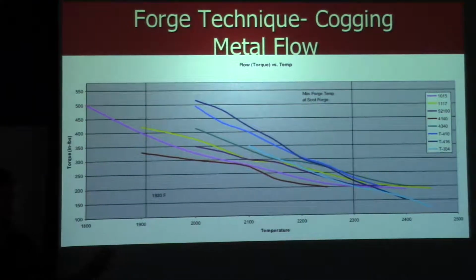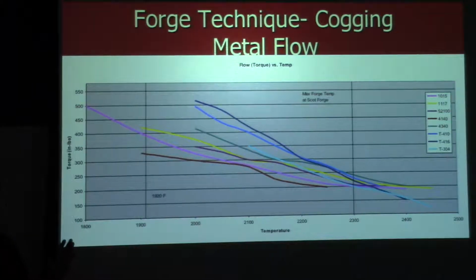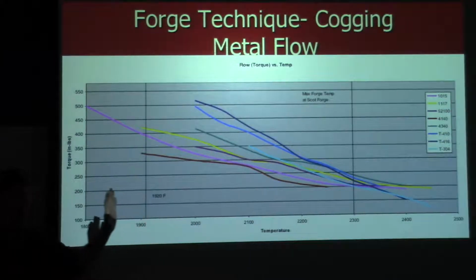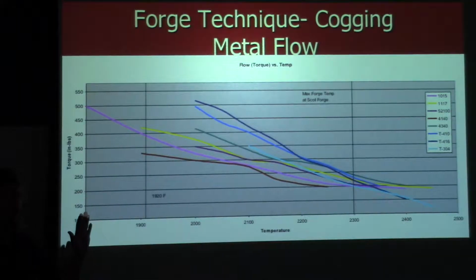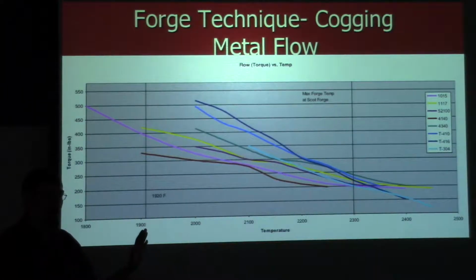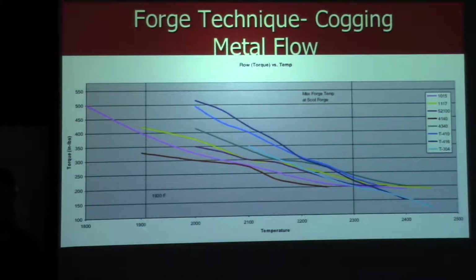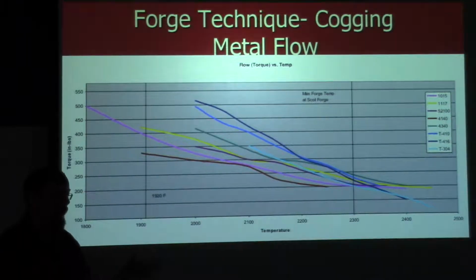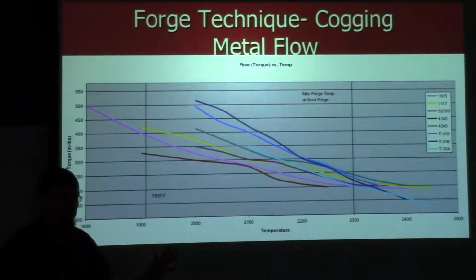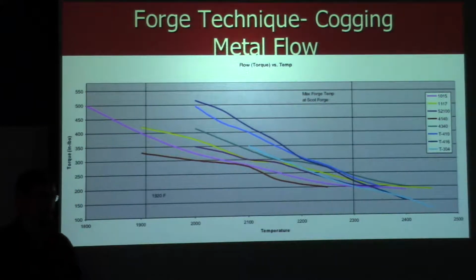So your forging window is set by not melting on one end, and staying within the austenite phase field, but also being in a range where you can get dynamic recrystallization happening, because if that's not happening, you're just going to build up more and more strain in the part, and eventually it's going to want to tear apart and rip. So that's where our boundaries come from. There's also the non-physical metallurgy parameter that at low temperatures, it's harder to move the metal, it's less efficient, so you don't want to waste a lot of time either. There are multiple contributors there.